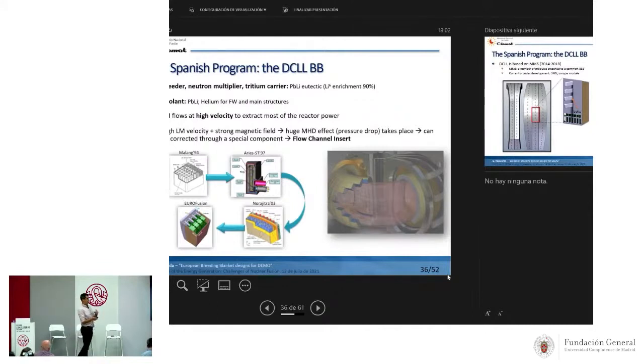One important characteristic of the dual coolant lead lithium, the DCLL, is that the liquid metal flows at high velocity because we want to extract most of the reactor power. If we don't route the liquid metal at high velocity, it will heat up and heat up and heat up due to the neutron interaction, and we don't want that. So we have to flow the liquid metal at high velocity, and this has an additional consequence. The immediate consequence is that we have a metal moving in a strong magnetic field produced by the coils, and we produce huge magnetohydrodynamic effects. Magnetohydrodynamic is a combination between the magnetic field and the hydraulics of the liquid metal. And to avoid this, I will go into the technical issues later, the DCLL uses a quite important and special component. It's a ceramic component called the flow channel insert.